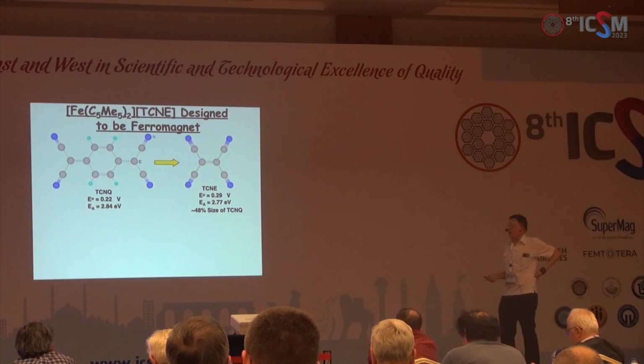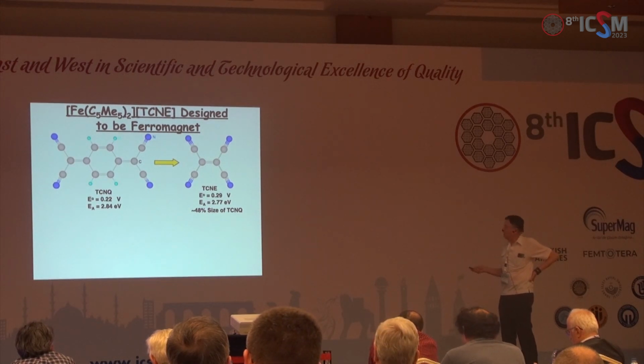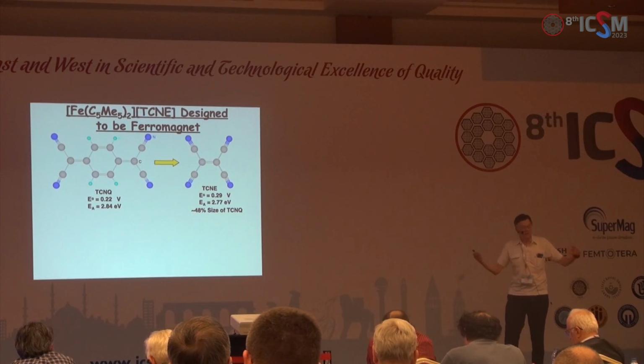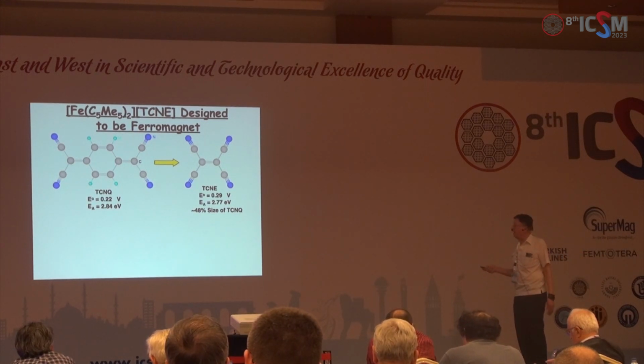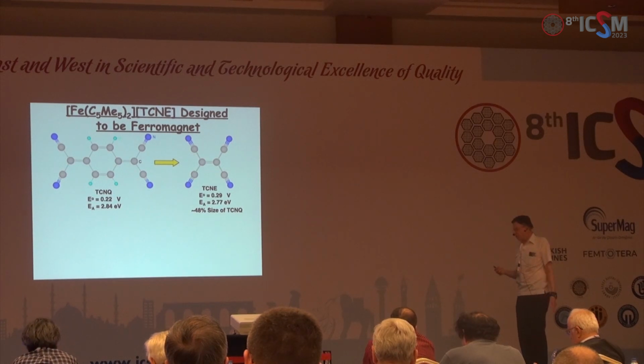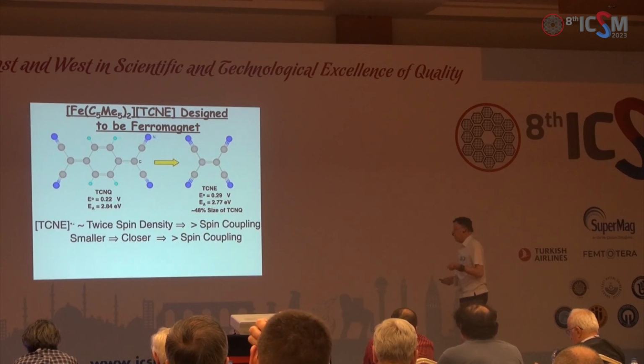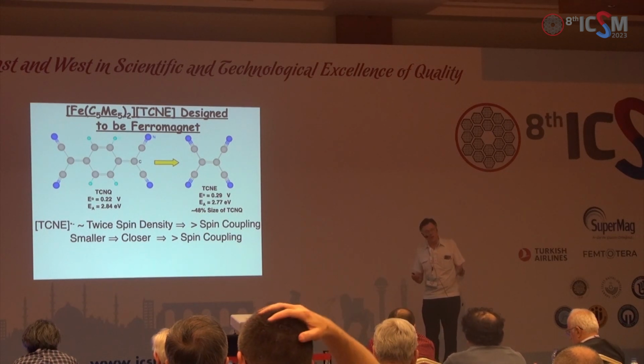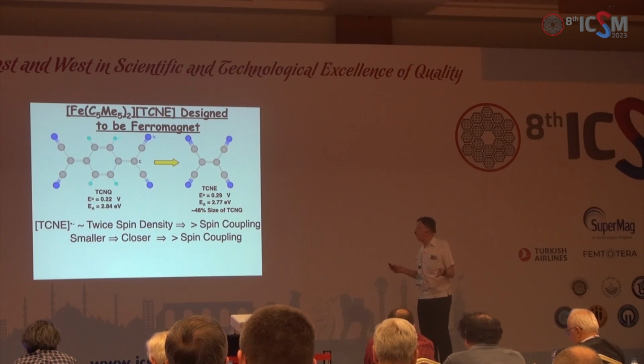So we hypothesized that if we can take this benzene ring out of the TCNQ, you would make TCNE, tetracyanoethylene. It's like polyethylene, except instead of hydrogens on the carbon double bonds, it's got cyanide groups. And that's almost as easy to reduce as TCNQ, but it's half the size. So if it's half the size, with the same number of spins, that means the spin density is twice, and therefore it has stronger coupling.